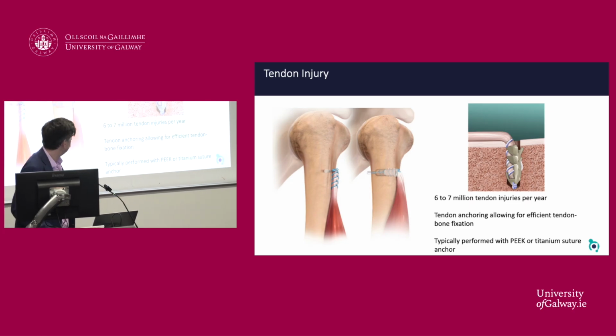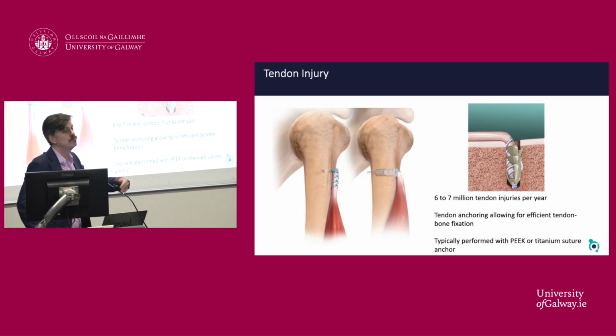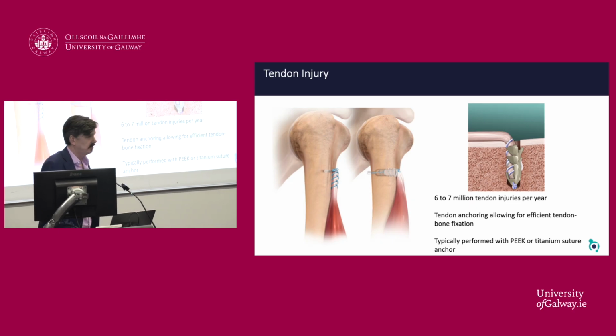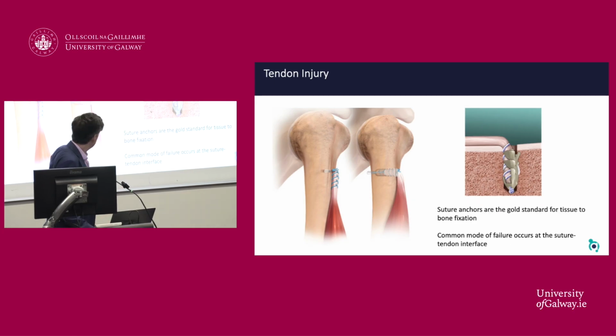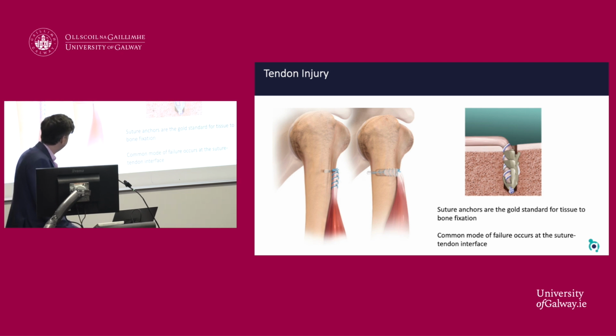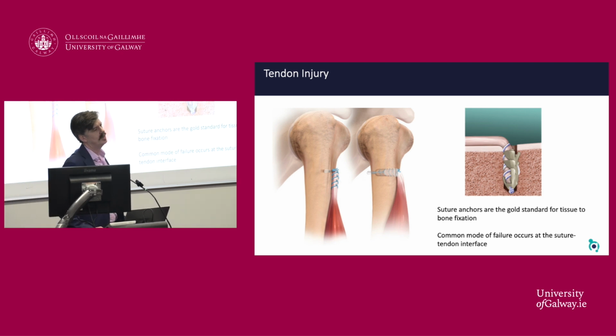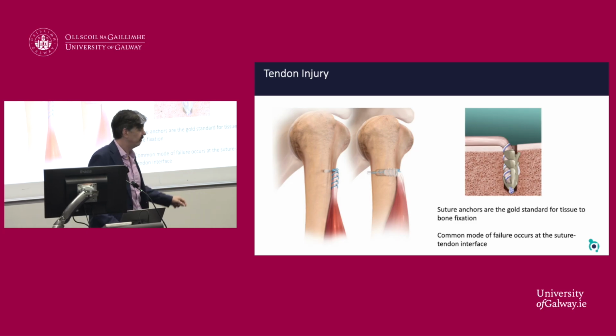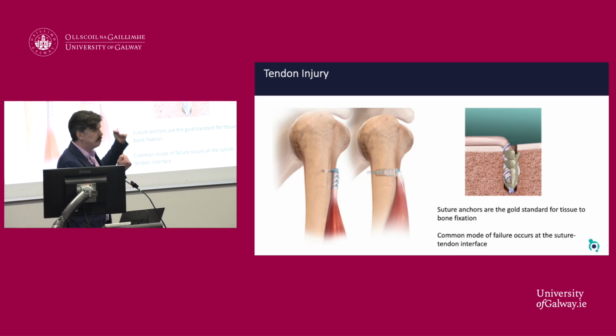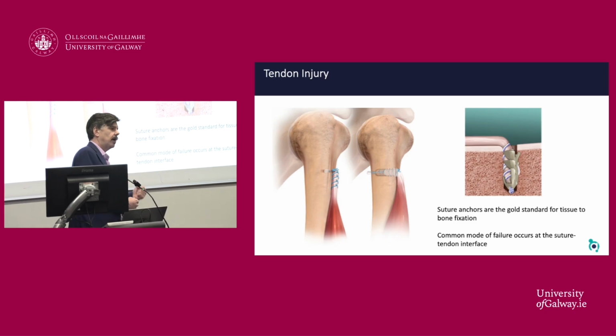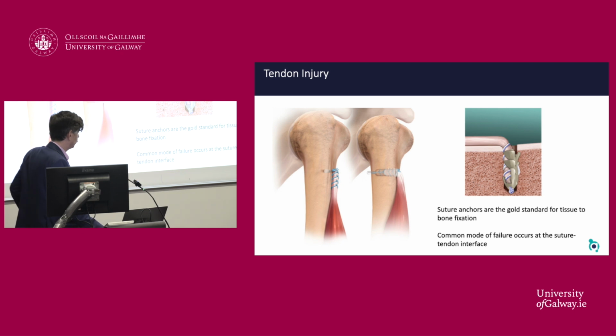These tendon anchors are typically PEEK, which is a polymer. It's a non-resorbable, really robust synthetic polymer, or titanium. So relatively tough materials. There are problems with these, however. Suture anchors are the gold standard for tissue-to-bone fixation. The common mode of failure occurs at the suture-tendon interface. So they're associated, again, with a relatively high failure rate. And the failure occurs as the tendon slips from the suture, or the anchor is pulled from the void. Essentially, it'll wiggle a little bit, and then eventually it will slip from the void that's been drilled by the surgeon. And this can occur relatively quickly, or over 2-3 years after this has been fixed.